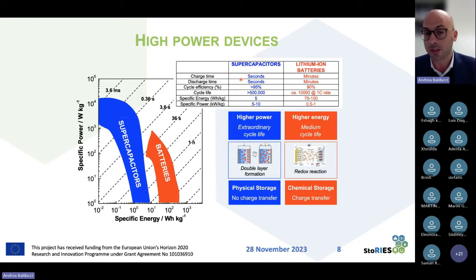Lithium-ion batteries are extremely efficient. They have a cycle efficiency higher than 90%, but supercapacitors are even higher, more than 95%. And this difference actually impacts the cycle life of this system very much, because a battery is always difficult to give a precise number for, but let's say a high power lithium-ion battery may stand for several thousand cycles, depending on the rate we apply. When we are talking about supercapacitors, we are talking about a device that has a cycle life in the order of 500,000 or even 1 million cycles, so extremely high cycle life.